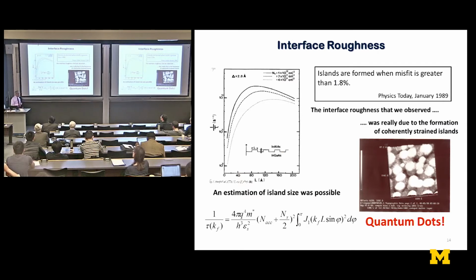It's absurd. It's nothing like a height of 2.8 angstroms and a lateral extent of a few angstroms. The height I get is much higher and so on. And I thought there was some mistake in the calculation, and I kind of forgot about it. But what we were really seeing, what his calculations were exactly right, and what it predicted was we were forming quantum dots at that interface, self-organized quantum dots, and which really looked something like this.